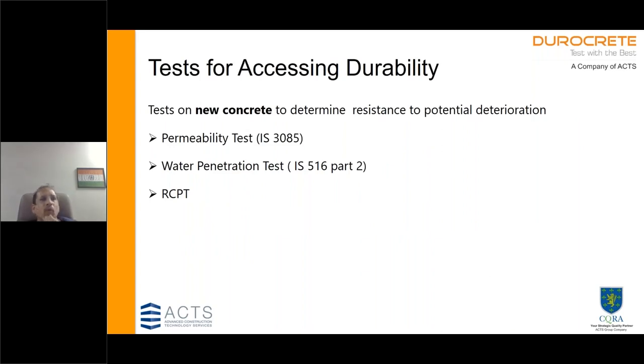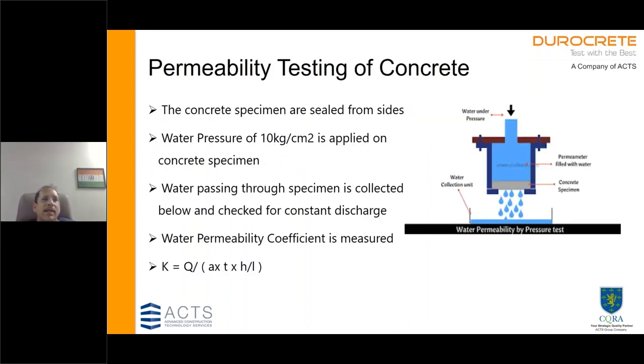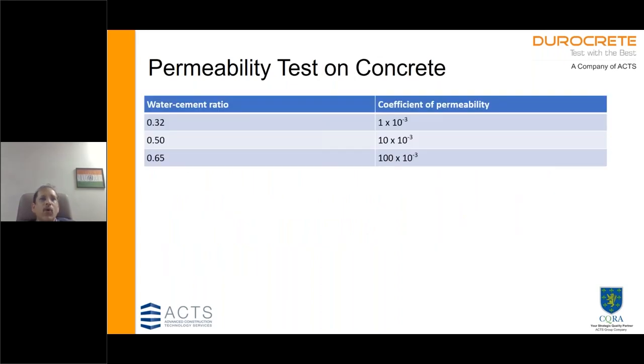So let us have a quick look at the tests that we do for assessing durability. The concrete specimens, the standard tests are permeability test. This is a traditional test where the concrete specimen is put under pressure of 10 bar, and we wait till there is a continuous trickle of water, that is a constant discharge, and we use Darcy's law, K is equal to Q upon area into the length of the specimen, and we find the coefficient of permeability. So lower the coefficient of permeability, more impervious the concrete.